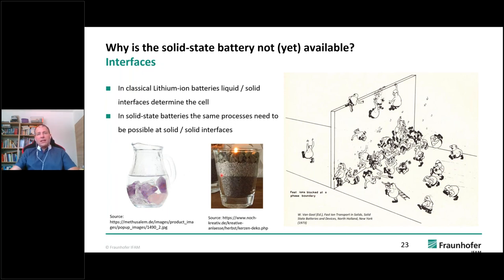And when we go to a solid state battery, which can be seen in this candle that I found on the internet, we have these stones lying on top of each other, but a lot of holes inside, the porosity. Wherever we have porosity and no connection between the particles, we have no transport. This limits the efficiency of our cell.